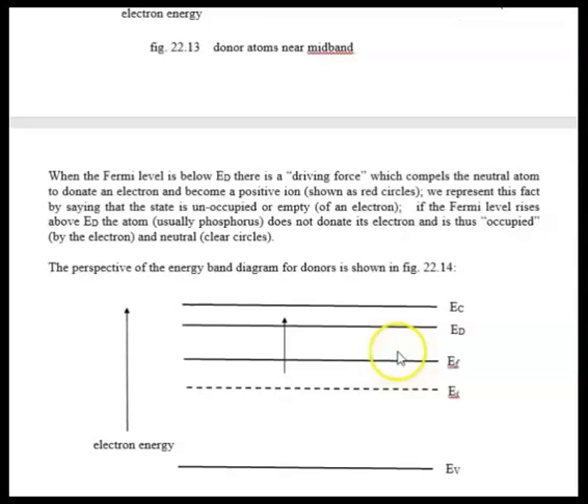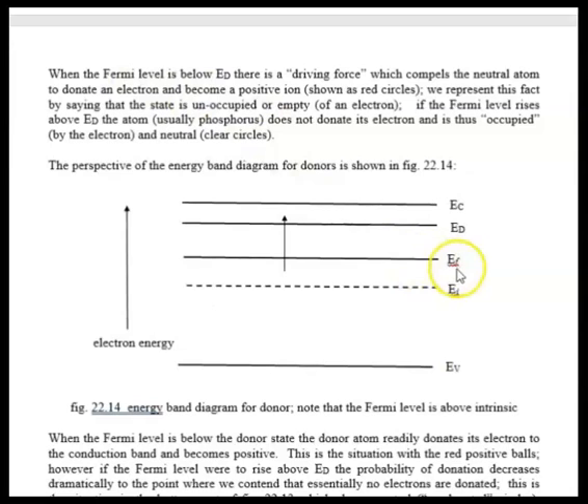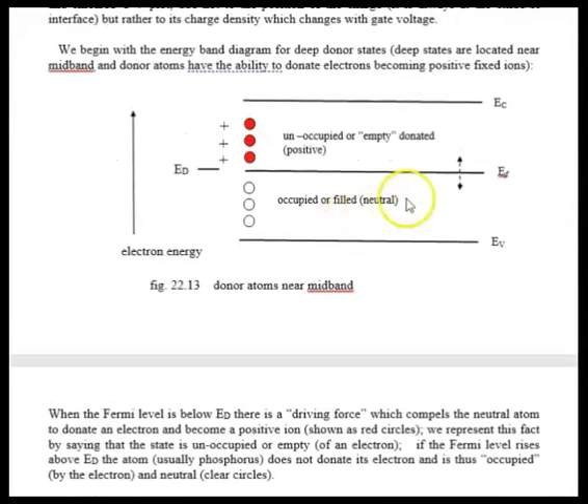So let's look at that in a little bit more detail in the more conventional donor atom, which would, for example, be phosphorus. This is drawn a little bit not to scale. This donor state probably should be a little bit closer to the conduction band. But the point is that if the Fermi level is below the donor state, which is shown here, then there is a driving force represented by this arrow, which pushes the atom, in this case phosphorus atom, to donate an electron. If, however, the Fermi level rises above, so the Fermi level is up here, then the donation pretty much stops. And that's exactly what we're showing here.